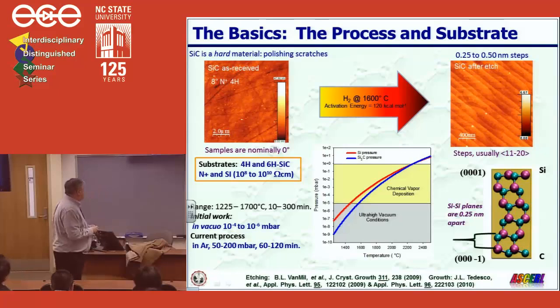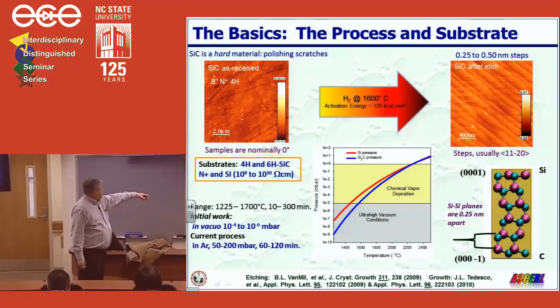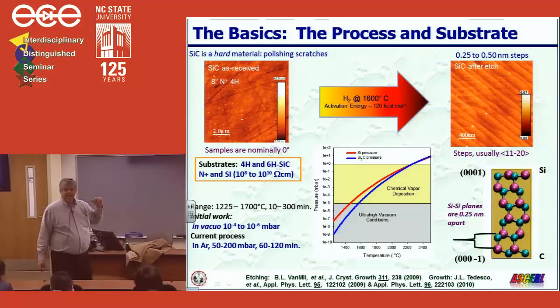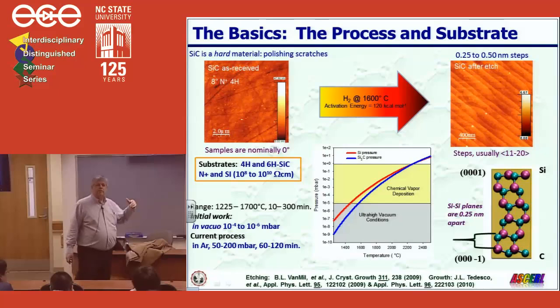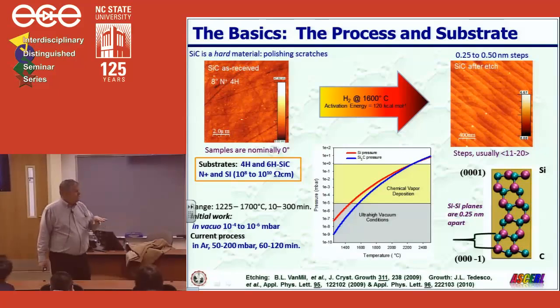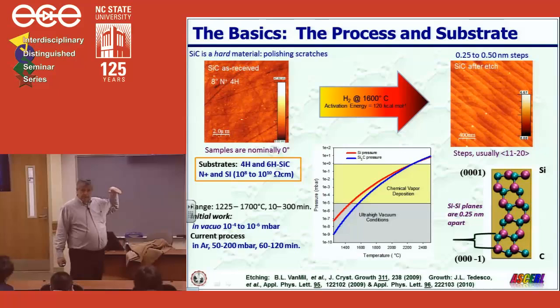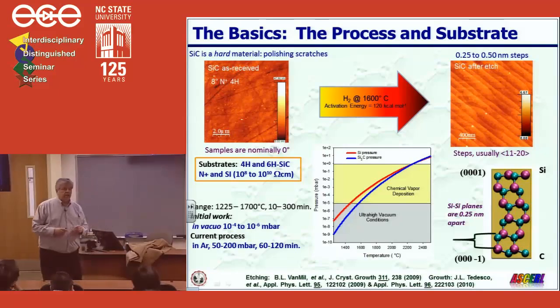So here's the process. We take our as-received wafer, and I chose this one because it shows all those polishing scratches. And then we etch it in 1600 degrees of hydrogen. We remove something on the order of 200 or 300 nanometers of silicon carbide, and it leaves a flat surface. Well, it's about as flat as you can expect. There's no such thing as buying silicon carbide that's perfectly oriented. So there's always going to be a slight tilt. And after you finish etching it, you will get steps and terraces. And this is an example of the steps and terraces as you would see from an AFM image. And the steps are on the order of 0.25 to 0.5 nanometers high. So it's actually pretty flat.